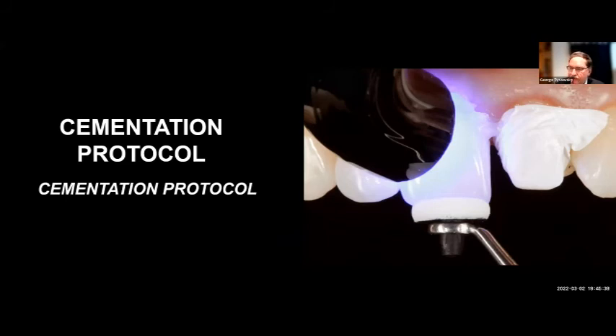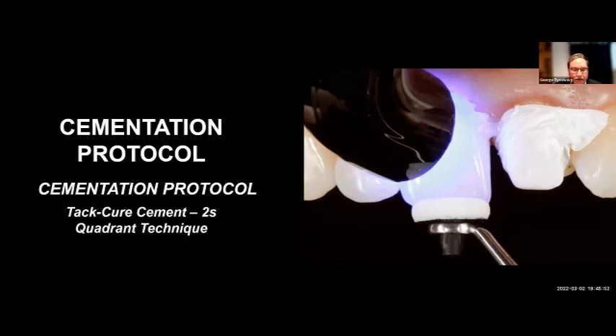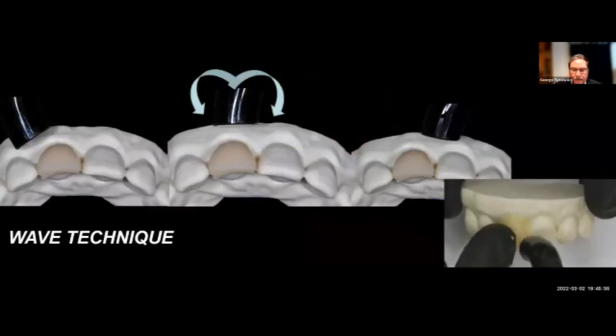So we've had interface dynamics. The tooth's been treated, the restoration's been treated. We load the restoration with our dual cure resin cement. We seat it. We cure it in a wave format. So we tack cure it, carve off the excess, and then can basically go ahead with final polymerization of the restoration. So this is a very popular technique. We're showing you here the wave technique.